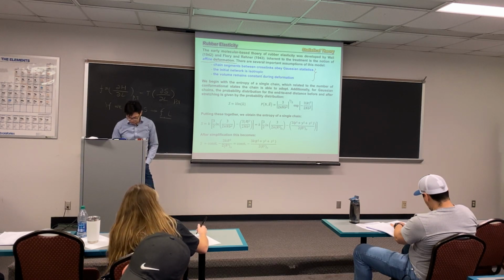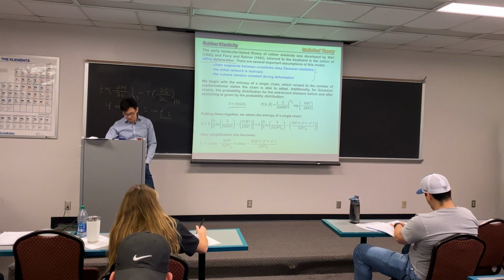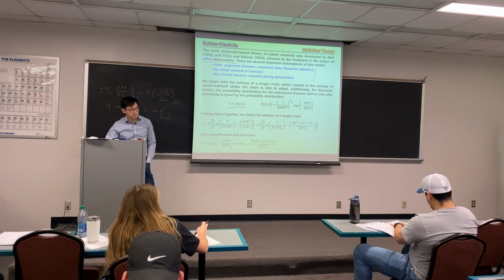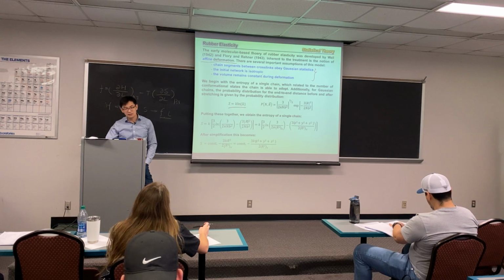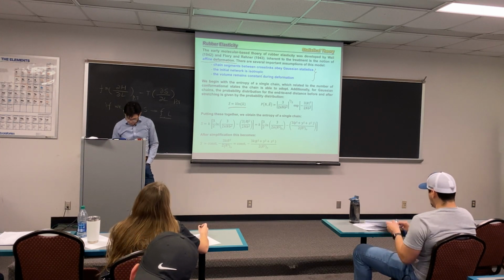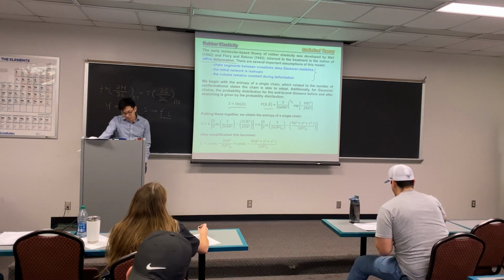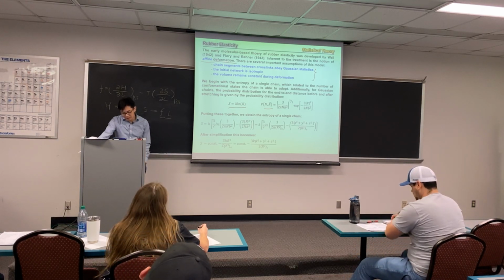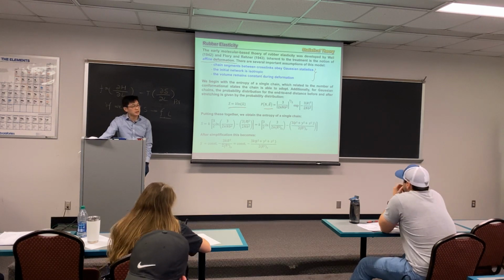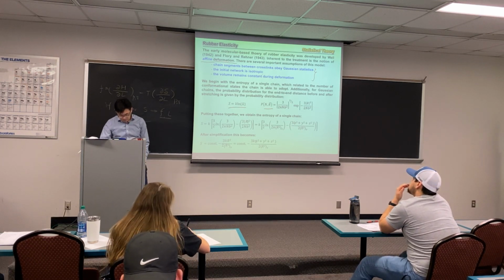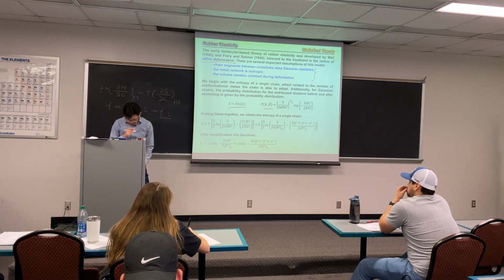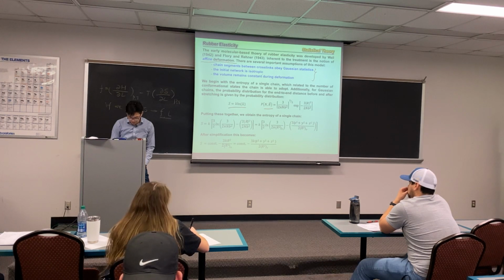If we use those three terms, then we can easily apply them to the entropy. This is what we have now. Your entropy would equal the Boltzmann constant k times log omega, the possible states of arrangement. And we know the probability of states, the probability of the chain end, is proportional to r. So if you apply those two together, you can get the entropy for your polymer.